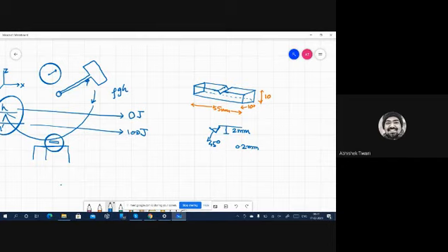Whatever technique you use, except one, at some scale it is going to have a root radius. So if you are doing electric discharge machining with a wire cutting, the smallest wire will also have a diameter of its own, right? So if you are cutting it with a wire, then the wire will give its own root radius at the tip, and usually the smallest wire is 0.2 millimeters.